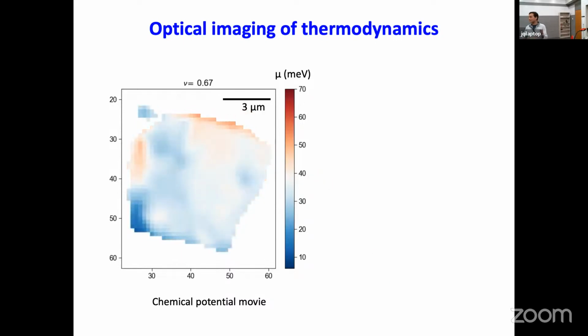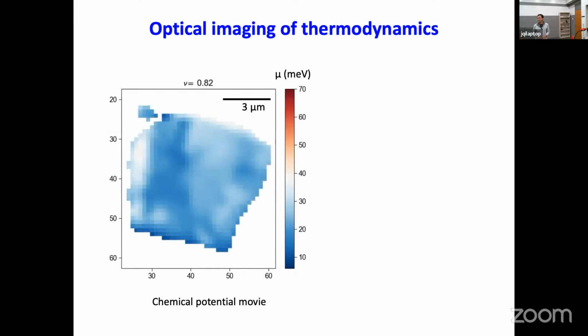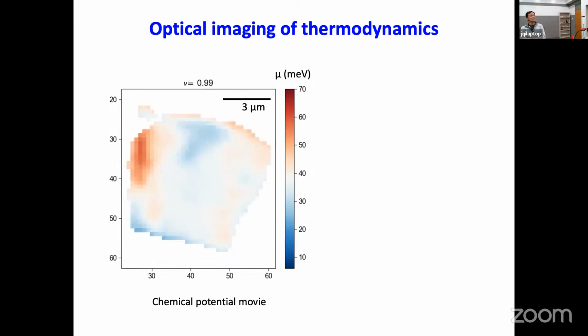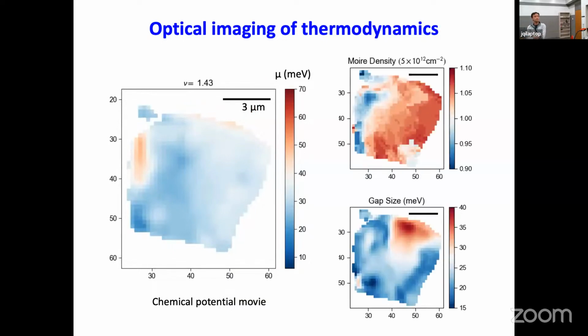We pick a particularly inhomogeneous sample to actually show that this technique works. And you can see that near filling factor 1, there's a quicker change because of the gap size. There's a charge gap in the system. But yeah, you can easily acquire a chemical potential map with about submicron spatial resolution.